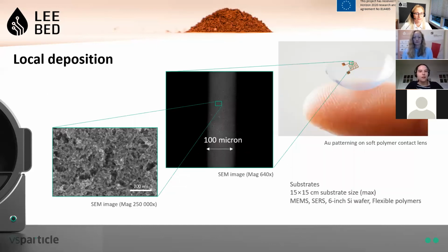And here I have 3 pictures of different magnifications of the printed lines. On the right upper corner, you see a gold pattern that is printed on a contact lens. And if you zoom in on such a gold line and look at it under an electron microscope, you see a nice crisp line that is 100 micron wide in this example. And if you zoom further in with your electron microscope, you see the porous structure of the gold that provides a large surface area and a large porosity.